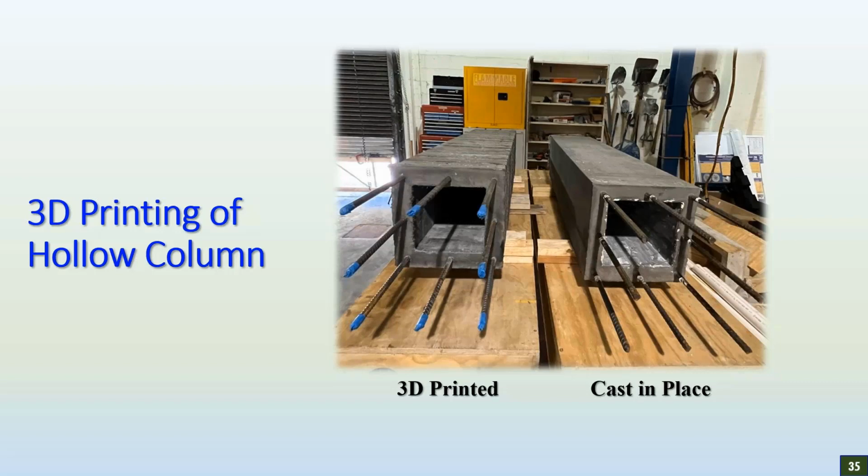Of course, there are commercial versions, and some people have given very high numbers, but you have to remember those high numbers, in some cases, involve certain equipment, technicians, times, and everything else. I can only comment on the open source because we have the numbers on that: anywhere between $500 to $800 per cubic yard, and it can probably go down even a little less than that. This is using the 2% steel fibers that is used in general UHPC.